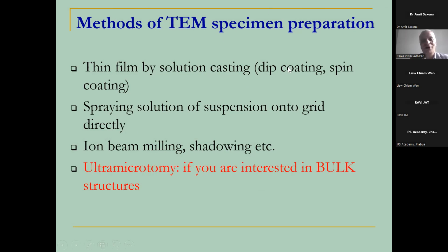And we can utilize the so-called dip coating method. Dip coating is taking the substrate, a clean and very flat surface, dipping it into the solution and taking it out with a particular speed. And spin coating is, of course, putting the solution onto a rotating disc and spinning the disc with some given speed. So that is called spin coating. And this is a very, very popular technique for preparing thin film for transmission electron microscopy.